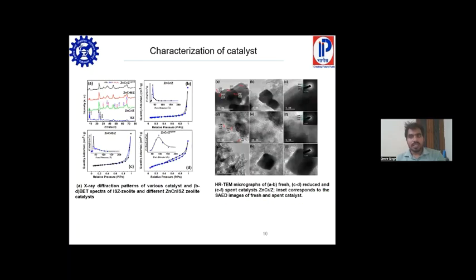Then come to characterization part of the prepared catalyst. First of all, XRD of the zeolite supported catalyst shows crystalline peaks at different planes. After the addition of zinc and chromium, the peak intensity changed and extra peaks were observed, which are due to zinc oxide and chromium oxide. In the case of the spent catalyst, the peak intensity is decreased, which is due to coke